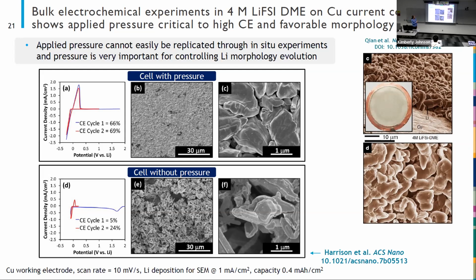So we did an experiment outside of the TEM where we replicated a cell with pressure, a coin cell type of cell, and we get much higher coulombic efficiency, and we're able to replicate the beautiful morphology that was shown in this paper. Then we took a beaker cell without any pressure, and we did the same experiment. And we get very low coulombic efficiency, and the morphology is much less well controlled. And we see clear evidence of dendritic growth of these lithium deposits.